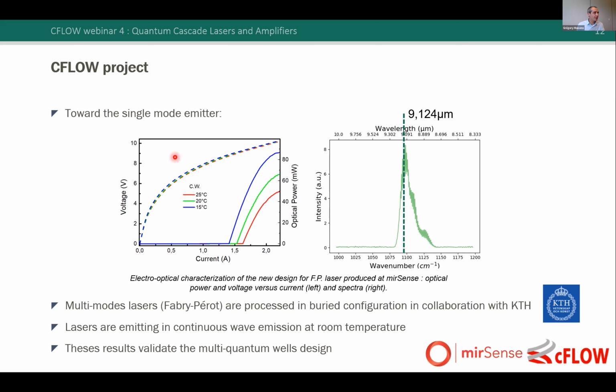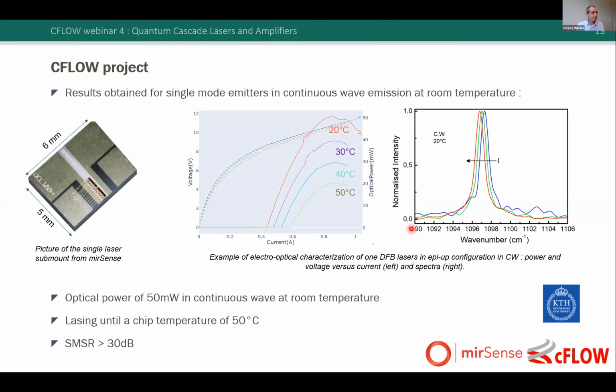You can see on this graph the evolution of the voltage versus the current and the optical power versus the current for one of these devices at different temperatures. So we have around 60 milliwatts at 20 degrees. But the most important is the fact that the spectra show that the gain is properly placed compared to the targeted wavelengths we want to achieve. So thanks to those results on the multimode lasers, we move forward to the single mode lasers.